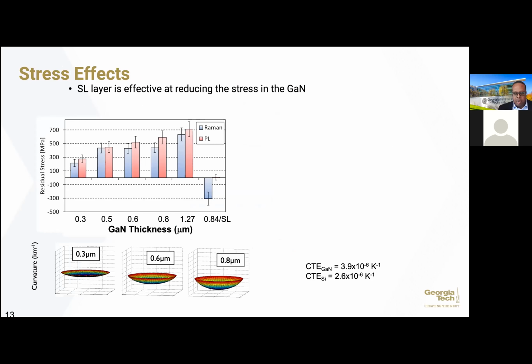So what we've been able to do is working with some commercial companies, looking at what happens as you grow gallium nitride on top of these superlattice structures, as well as on top of the aluminum nitride. So this is just showing you with the gallium nitride going from 0.3 microns out to 1.27 microns, you can actually see the stresses in the GaN increase. You can see the bow of the wafer also here increase. And so what I'm doing here is I'm using Raman spectroscopy as well as photoluminescence. Why do we use those two measurements? Raman spectroscopy gives you the average through the thickness of the GaN. The photoluminescence gives you the stresses right at the surface. And so I can begin to look at gradients and the stress gradients in the material.